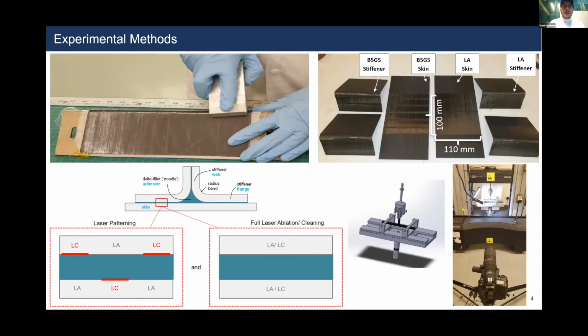So for the experimental methods, it was a simple manufacturing process, a hand lay up, where CFRP prepregs were laid up with the respective stacking sequence on a mold, and then the fixture was closed and the stiffeners were cured. The skins and the stiffeners were manufactured separately, and after they were cured, they were bonded using a special adhesive. They underwent laser treatment before being bonded. The areas which were treated were the bottom of the stiffener and the top of the skin, and these were the areas of contact. So this is, for example, what you would see from a patterning. The dark area is the laser ablation and the light area is the laser cleaning. After applying the laser irradiation on the surface of the adherents, they were bonded using an Araldite 420 AB adhesive. And after curing, the T-joints were tested using what is known as a pull-off test, which simulates out-of-plane loading in real conditions.